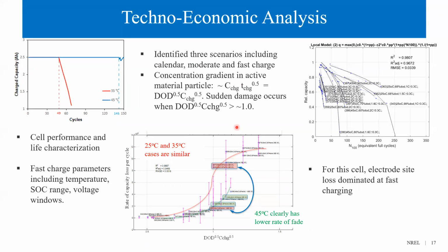but temperatures. For example, moderate charging rates are defined as less than 1 C at 25 degrees Celsius, and less than 1.5 C at 35 and 45 degrees Celsius. This is related to the concentration gradient in active material particles, calculated by charging and discharging rate times square root of charging discharge time. The middle figure shows the rate of capacity loss per cycle as a function of concentration gradient, captured by a sigmoidal function around concentration gradient 1.